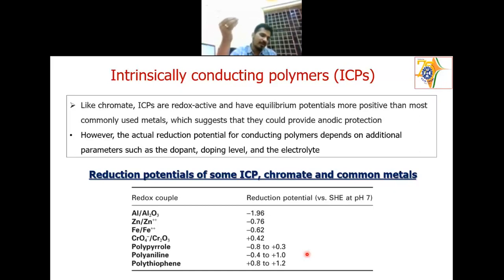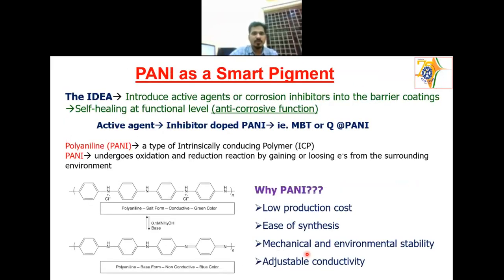Each conducting polymer can be doped using some kind of anions during the synthesis itself. We'll come to that in the next slides. So the idea is to introduce an active agent or corrosion inhibitor into the PANI as a dopant. That means you have self-healing at the functional level, that is, the anti-corrosive function. The active agent will be an inhibitor dopant; the inhibitor can be MBT or Q, meaning quinoline, or any other organic compound which is known as a corrosion-inhibiting pigment.